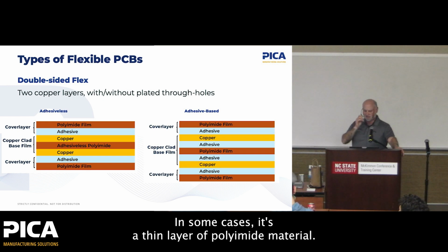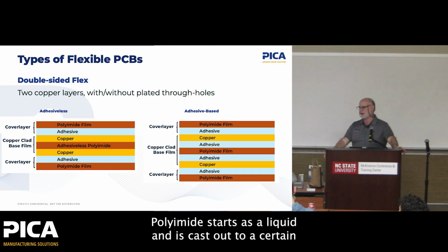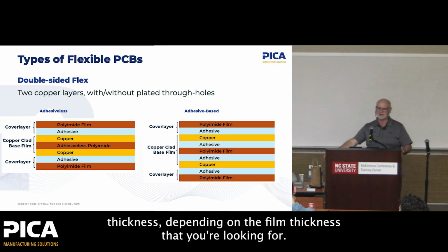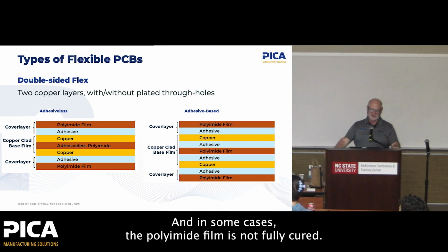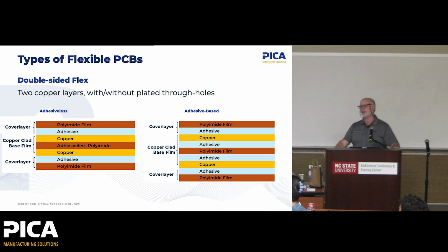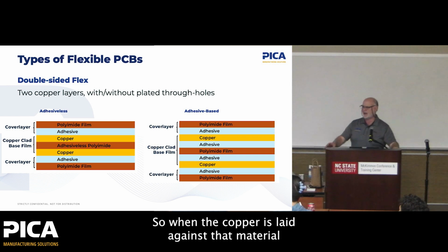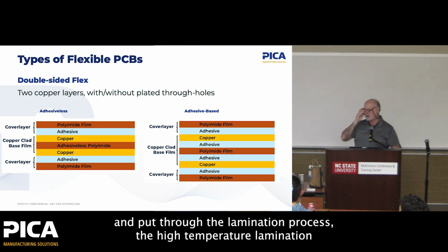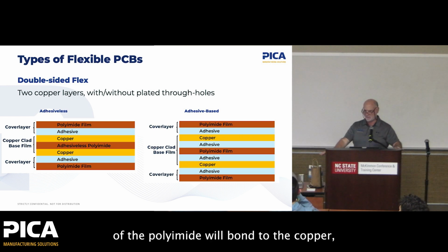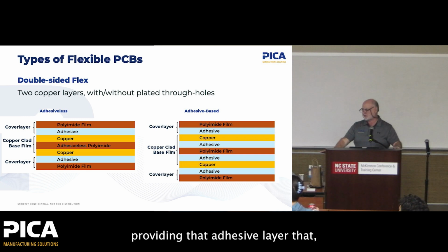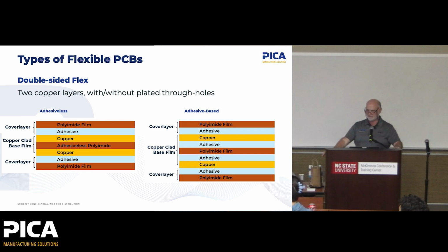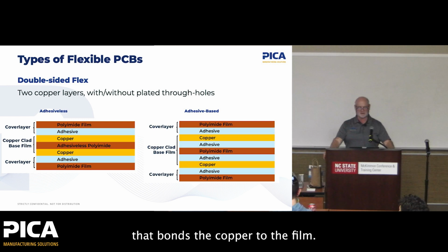In some cases, it's a thin layer of polyimide material. Polyimide starts as a liquid and is cast out to a certain thickness depending on the film thickness that you're looking for. And in some cases, the polyimide film is not fully cured. So when the copper is laid against that material and put through the lamination process, the high temperature lamination of the polyimide will bond to the copper, providing that adhesive layer that bonds the copper to the film.